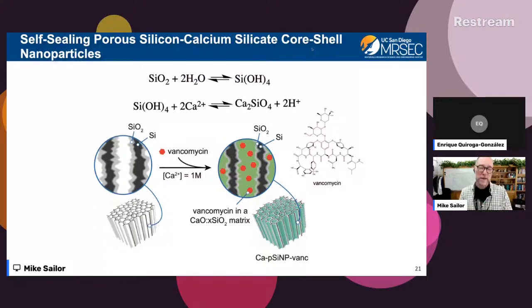If we add some calcium ion into the solution, we'll naturally form this cement, this calcium silicate phase within the porous nanostructure of our material. It's shown in the bottom part of this slide as an example where we added our silicon nanoparticles to vancomycin. Vancomycin is an antibacterial drug that we're going to be using here in a few minutes. That vancomycin gets trapped in the pores and sealed by this calcium silicate precipitation chemistry.